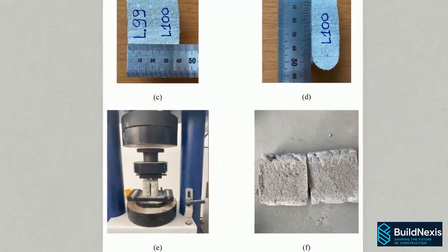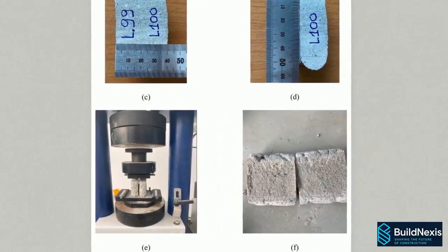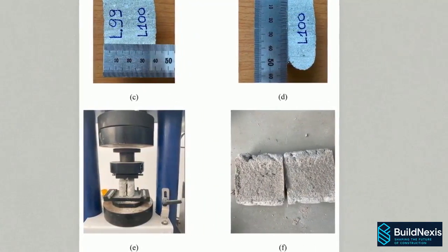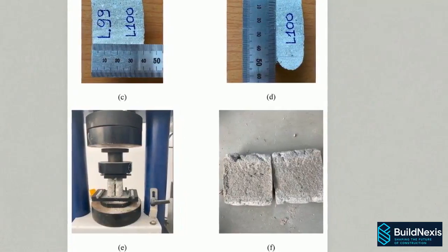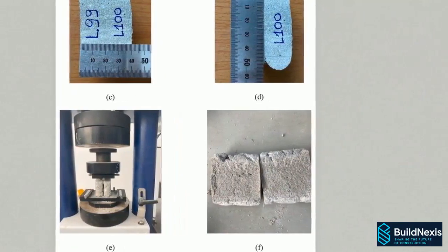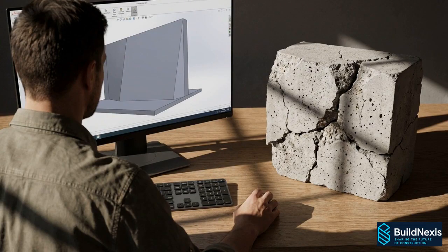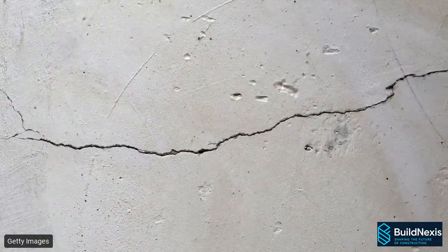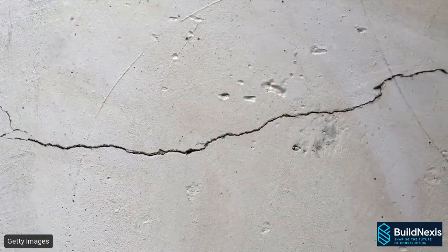A compressive load is applied perpendicularly to the interface. The pressure increases until the maximum stress is reached, forcing the layers to physically separate along the contact surface. Interlayer delamination is rarely caused by a simple printing error or a physical gap in the extrusion. These fractures are mechanically driven by differential shrinkage.